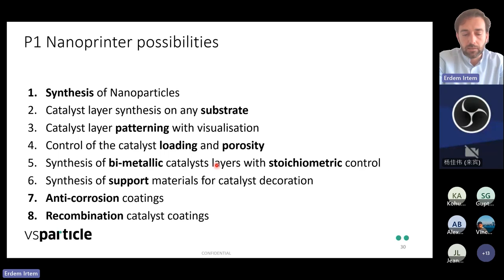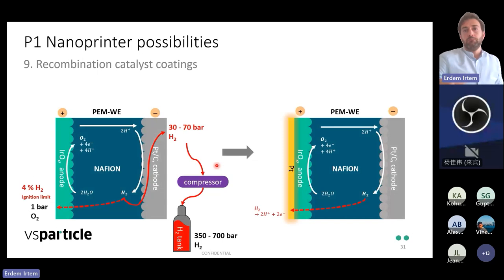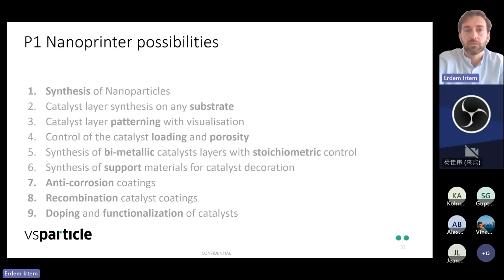Coming to the last two, recombination catalyst coatings are also quite attractive, because companies would like to conduct high pressure water electrolysis, which is around 50-70 bars. When there is a differential pressure from the cathode to the anode, like if the anode is operating at ambient pressure, it is highly possible that hydrogen gas could cross over through Nafion, and if it is more than 4%, this is at the ignition limit with the oxygen, which is posing a huge safety risk. So for that reason, a platinum back layer is applied so that this hydrogen is immediately converted back to the proton, to the hydrogen ion, so this positively charged ion will travel back to the cathode to react to hydrogen again. So this kind of back recombination catalyst coating could also be applied just like applying to the titanium felt, for example.